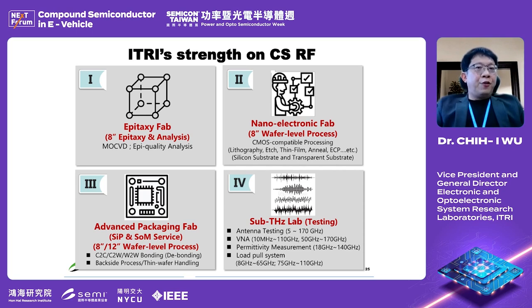For the high frequency application, our program has four parts. First, we have an epitaxy fab. We'll work on 8-inch epitaxy wafers directly on silicon. We know the industry now has gallium nitride on silicon carbide for 4-inch and 6-inch, and also gallium nitride on silicon for 6-inch. At E3, we will work on gallium nitride on silicon epitaxial growth on 8-inch wafers. We have already worked on epitaxy for many years, so we are quite experienced in gallium nitride epitaxy. So we have an 8-inch wafer lab at E3, and we will use this 8-inch epitaxy wafer to make the high frequency device.